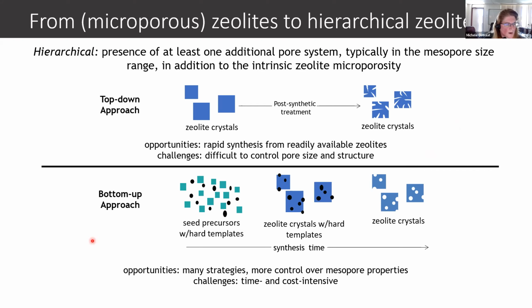There's another way you can do this, which is termed a bottom-up approach, in which you take precursors, so seed precursors, and either hard or soft templates. You then do a synthesis, and the hard template, for example, gets incorporated into the zeolite crystal. And then what you do is you burn off, you leach, you etch out the hard template, and you're left with this hierarchical zeolite. The opportunities here for the bottom-up approach include that there are many strategies to be able to achieve this. You also have some pretty good control over the mesoporous properties.